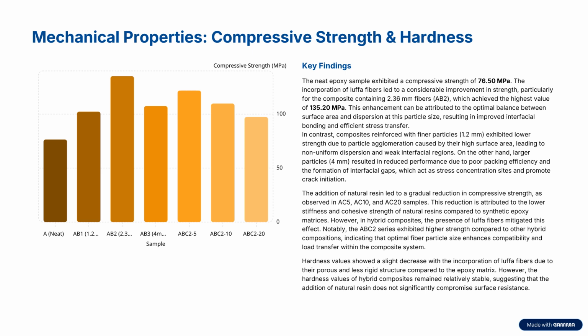Our results show that the neat epoxy sample exhibits a compressive strength of 76 megapascal. The incorporation of Luffa fibers led to considerable improvement in strength, particularly for the composite containing 2.36 millimeter fiber, AB2, which achieved the highest value of 135 megapascal. This enhancement can be attributed to the optimal balance between surface area and dispersion at this particle size, resulting in improved interfacial bonding and efficient stress transfer. In contrast, composites reinforced with finer particles exhibit lower strength due to particle agglomeration caused by their high surface area, leading to non-uniform dispersion and weak interfacial regions.